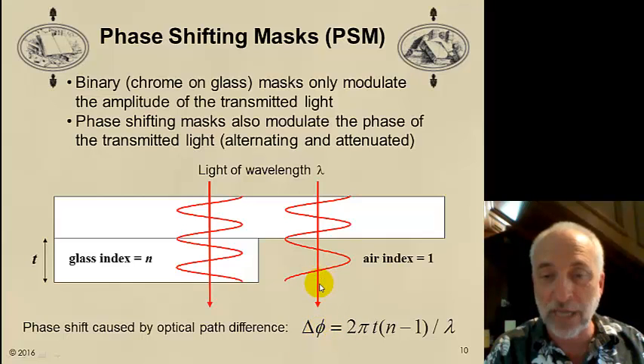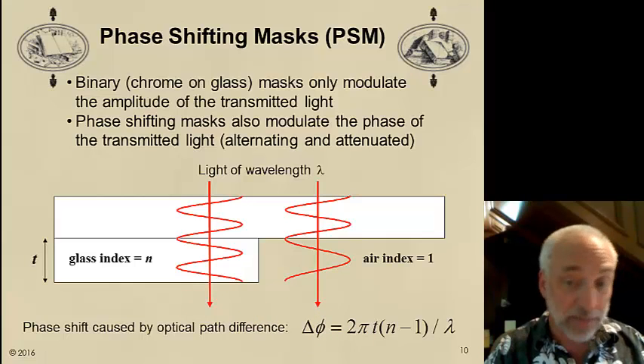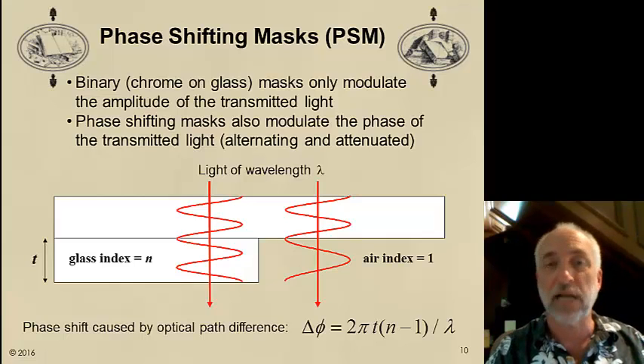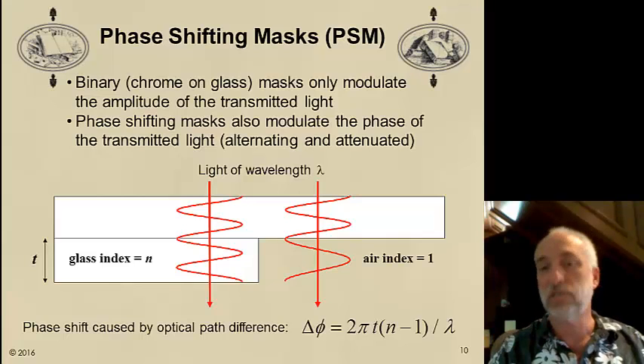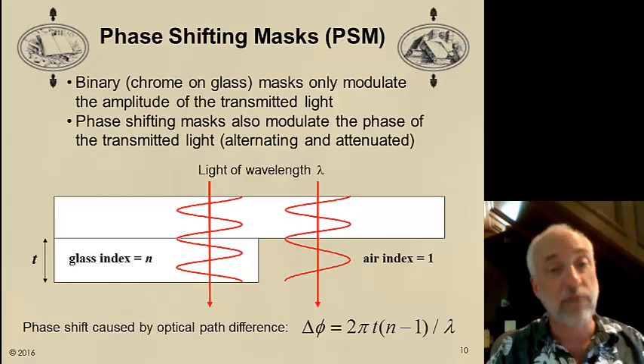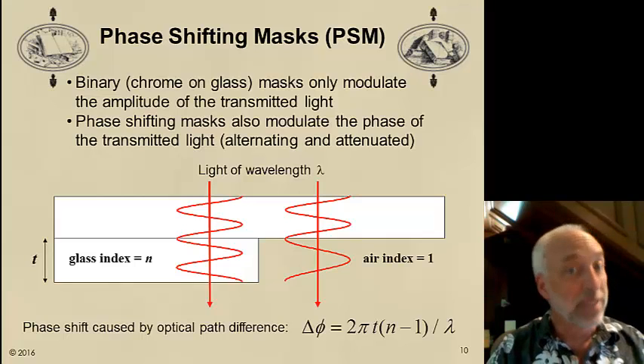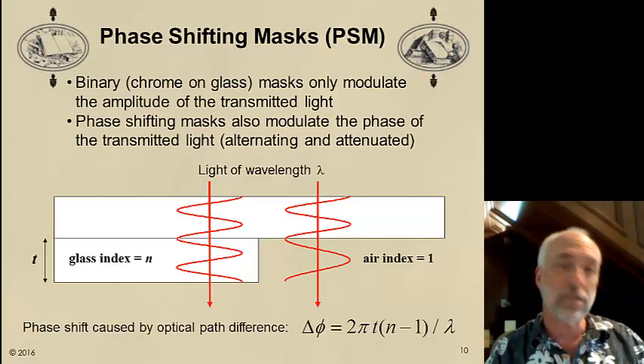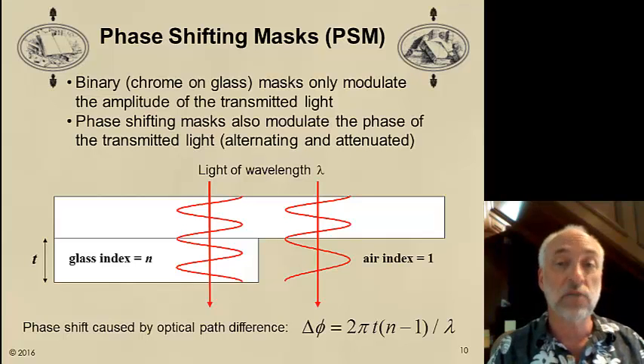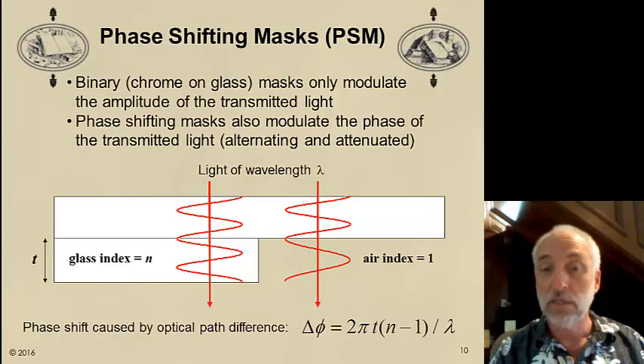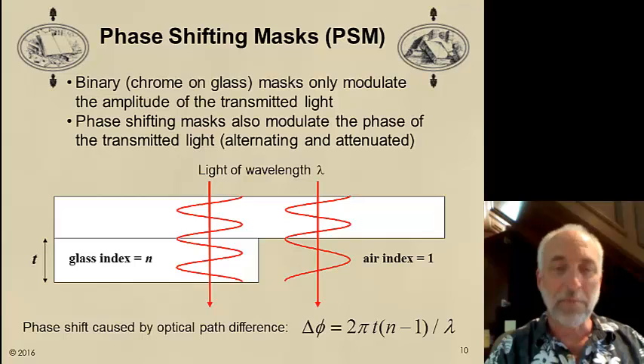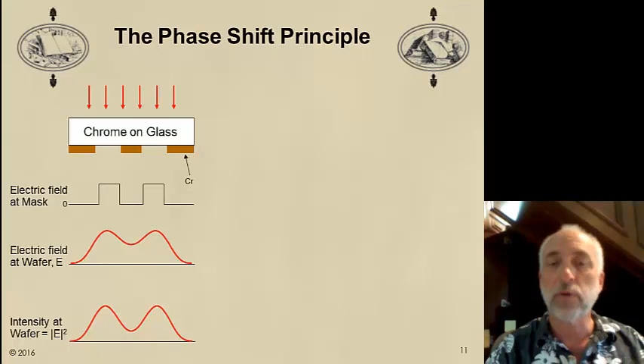Delta phi is the change in phase, or the difference in phase between these two rays. And you can see that it is 2 pi times the thickness of the glass times the difference of the refractive index between the glass and the air, all divided by the wavelength. If I adjust the thickness just right for any given refractive index, I can get whatever phase shift I want. But the phase shift that I always want is 180 degrees. A pi phase shift means that the light coming through the air is exactly opposite phase, 180 degrees out of phase, with the light going through the glass. What are we going to use this phase shift for? If we can make it by adding some extra glass, for example, what are we going to use this for?